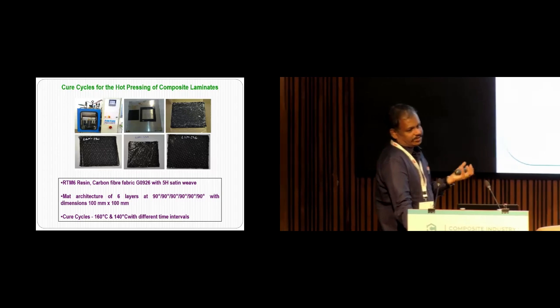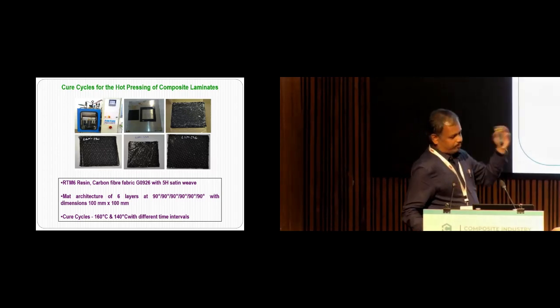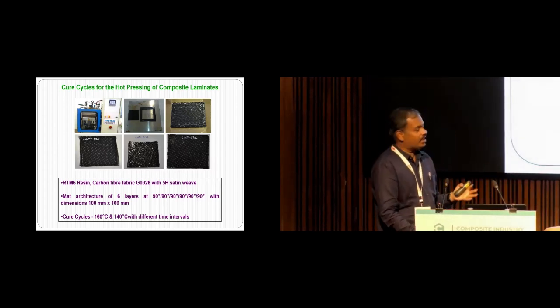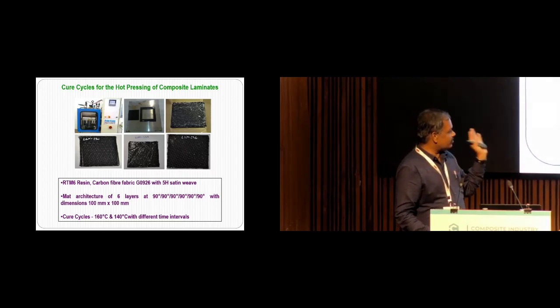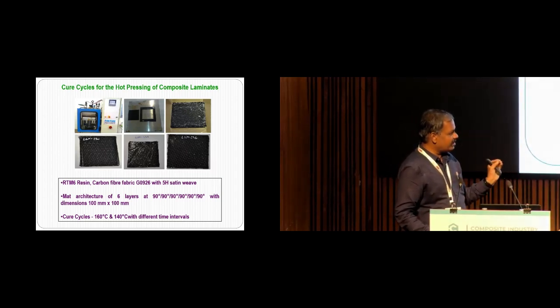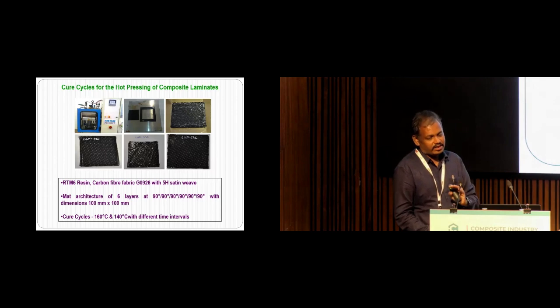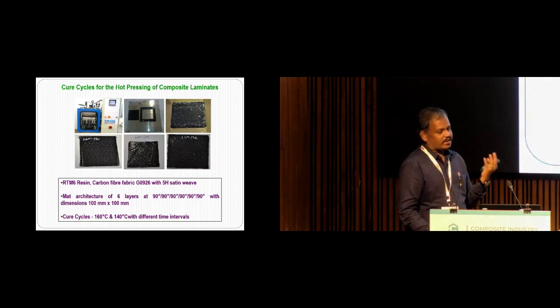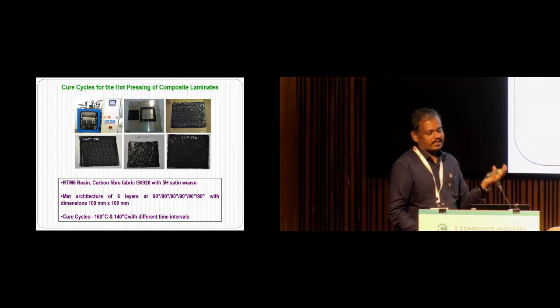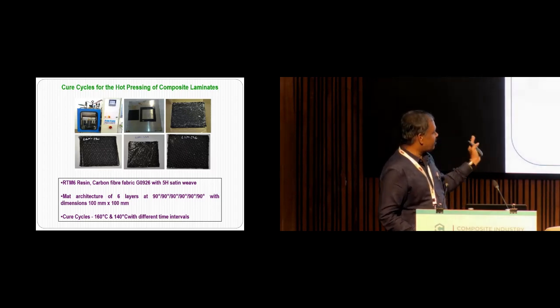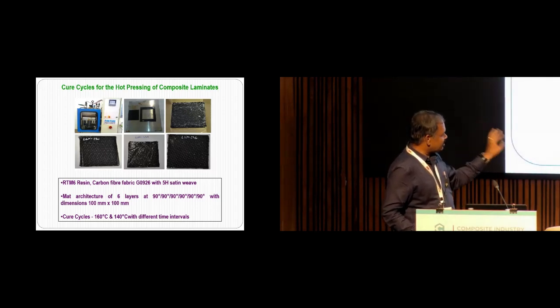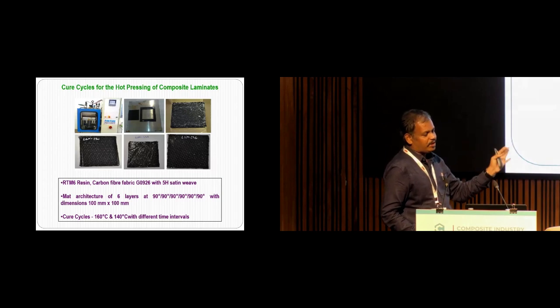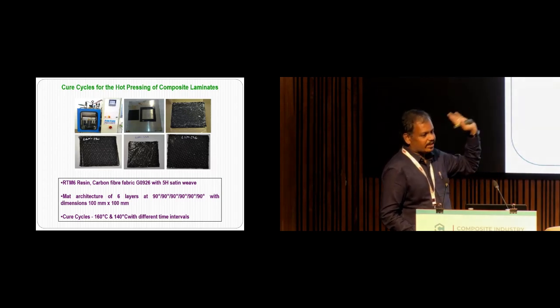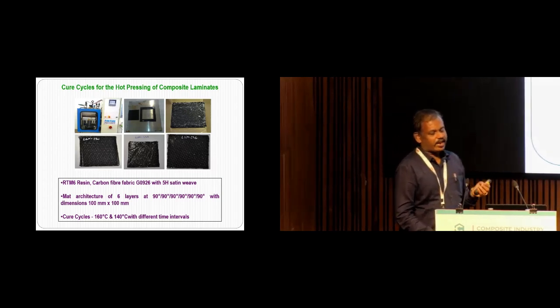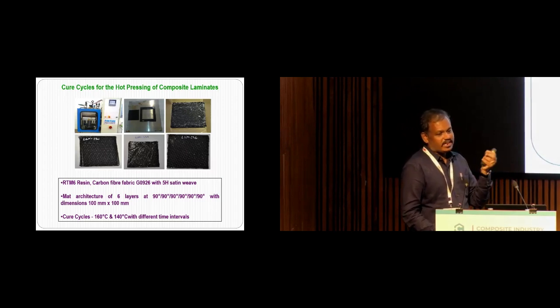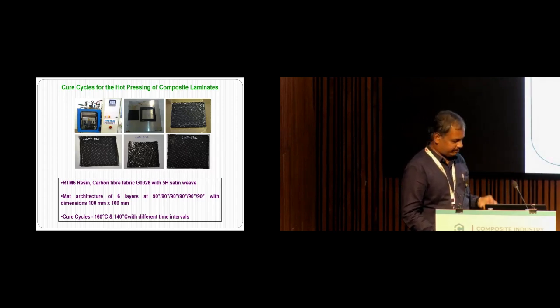Then, with respect to our previous plot, we thought that cure cycles at 160 degrees centigrade and 140 degrees centigrade with different time intervals would give optimistic results for a semi-cured panel. So we are going to apply 160 and 140 degrees centigrade with these time intervals in the hot press process, and study what the degree of cure of the composite panel will be.